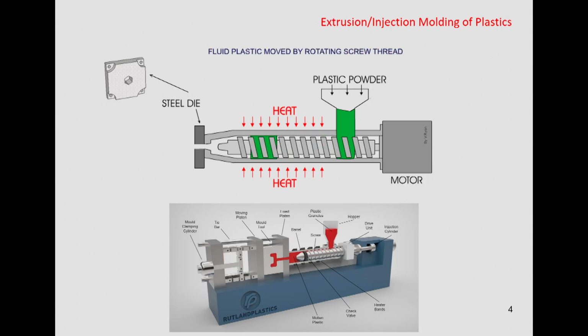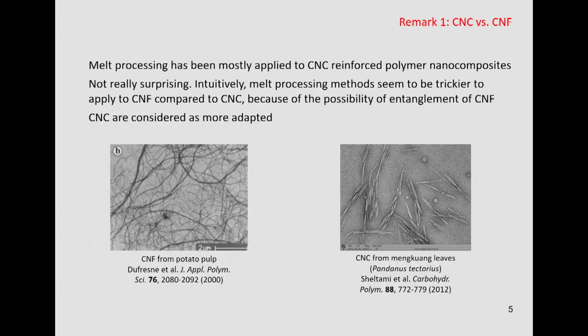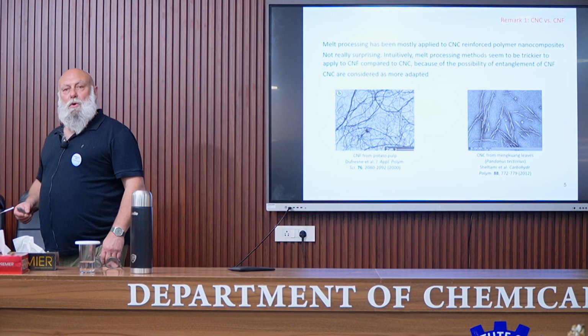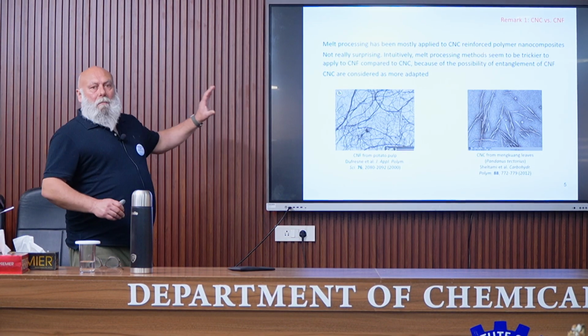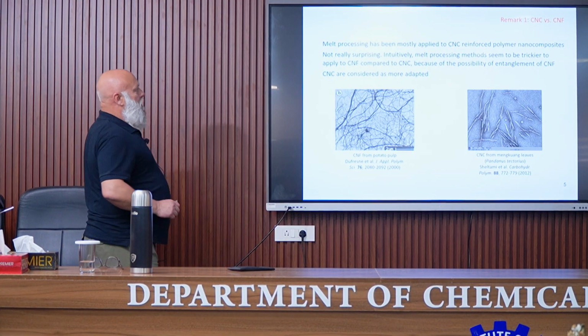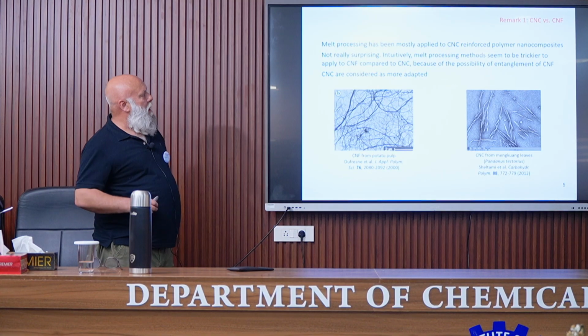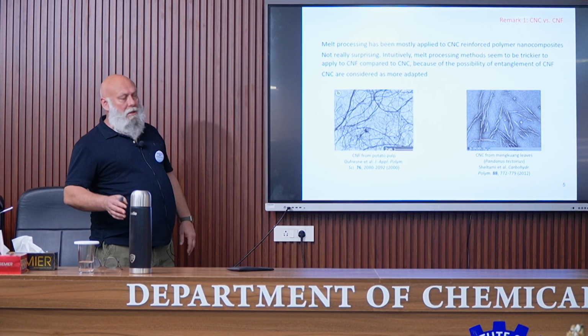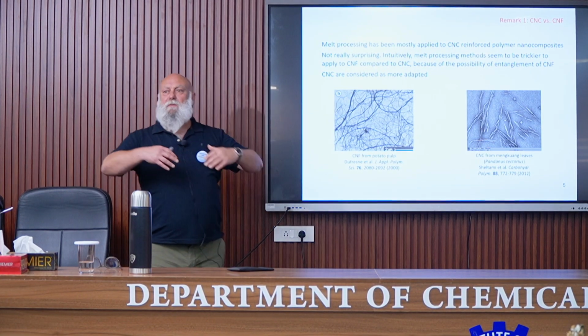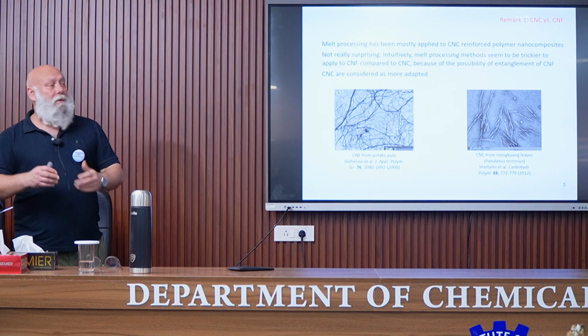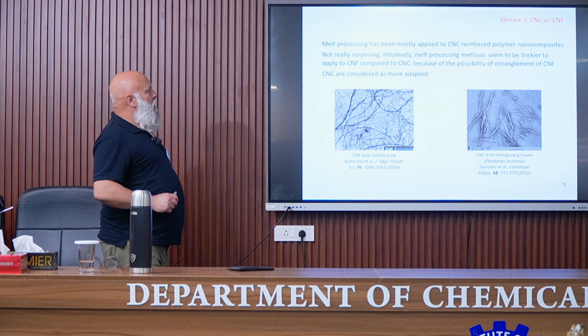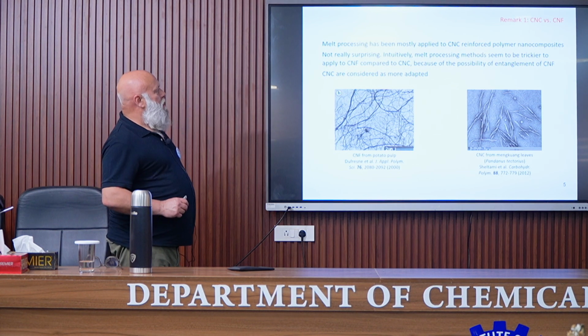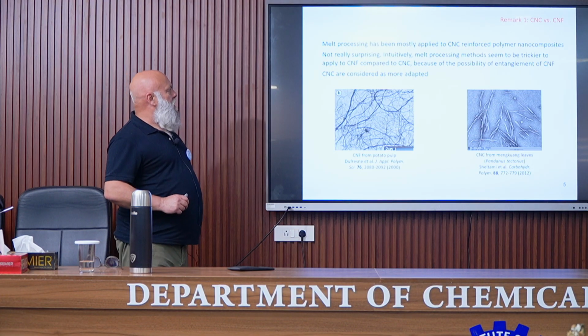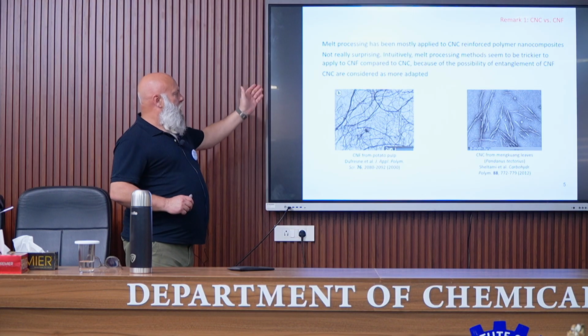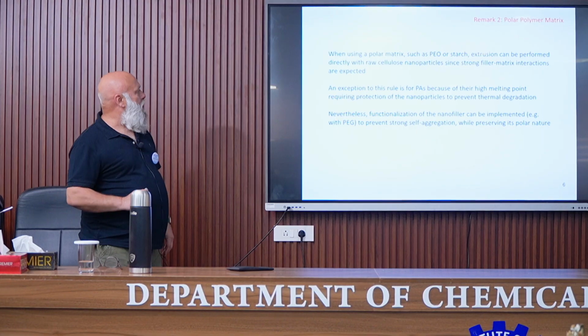Extrusion and injection molding, we have seen, are commonly used to process thermoplastic materials, and why not use this to process cellulose nanocomposites? Before that, I have some remarks. CNC versus CNF. Melt processing has been mostly applied to CNC reinforced polymer nanocomposites, which is not really surprising, because you imagine that these very long filaments can hardly be dispersed mechanically in a polymer melt. So melt processing seems to be trickier to apply to CNF compared to CNC because of the entanglement. So we can consider that nanocrystals are more adapted for melt processing.